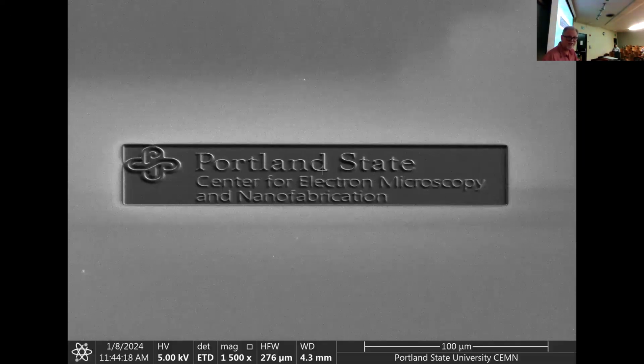And here we can see a much smaller version, if you were on the microscope, of the CEMN logo. I did that as a 200 micron wide mill. It's about 48 microns high. And this is just a silicon substrate. Silicon is ideal if you get single crystal for these types of things because it will mill very uniformly, being single crystal. It's the cheater's method, and I will cheat when I need to for something like this.